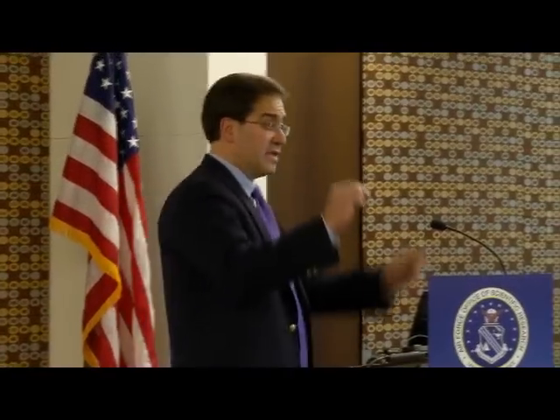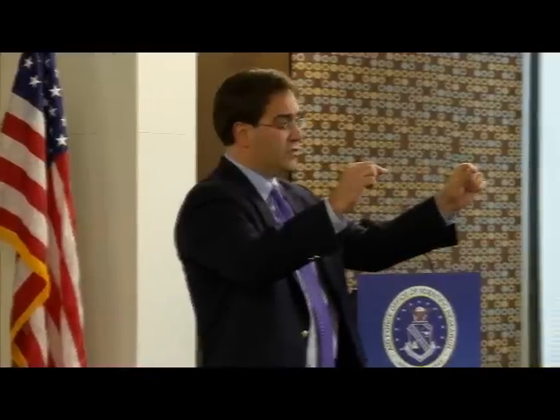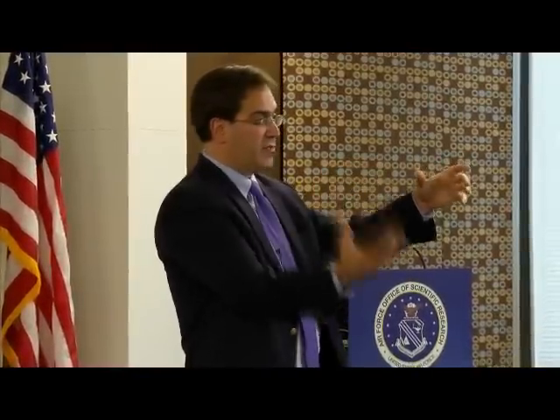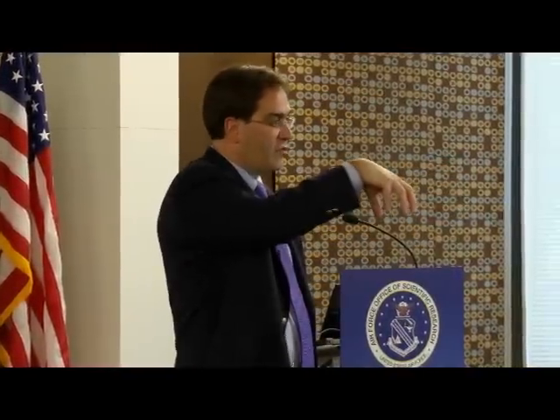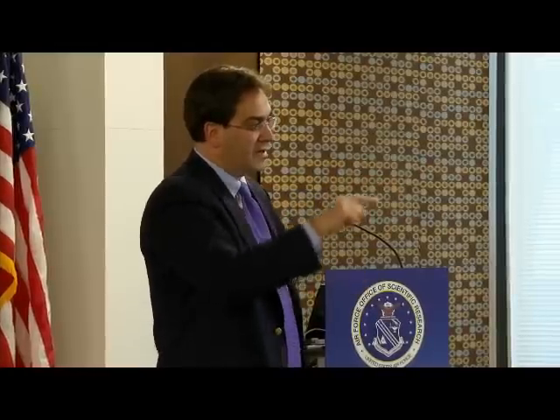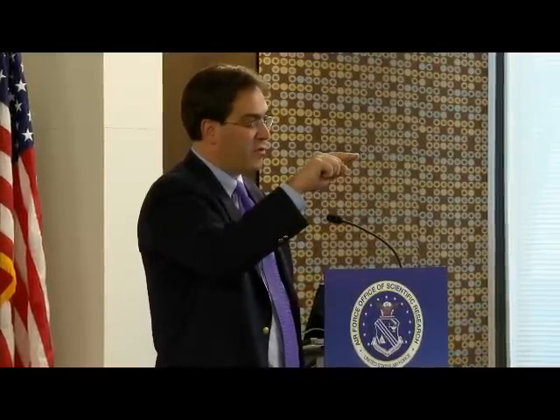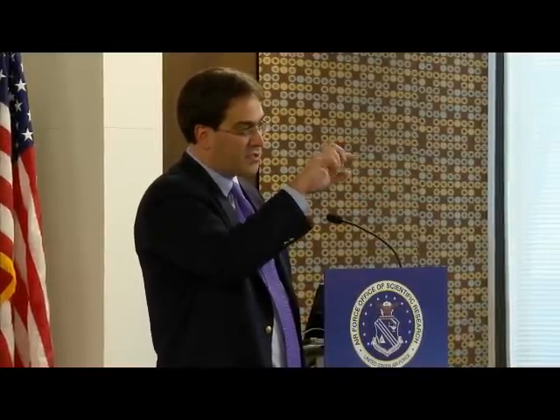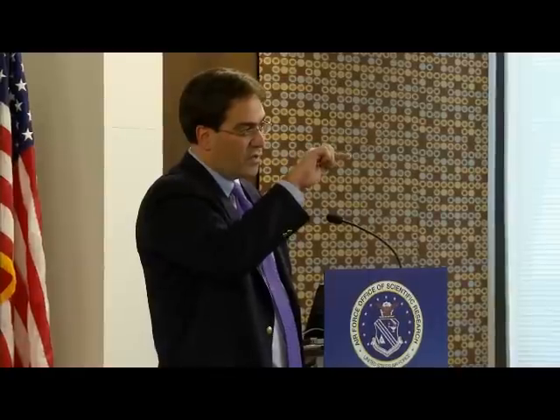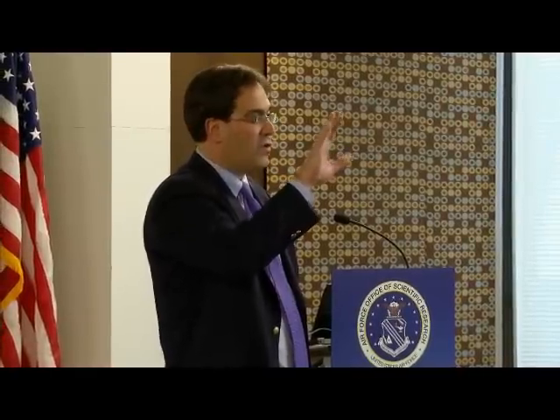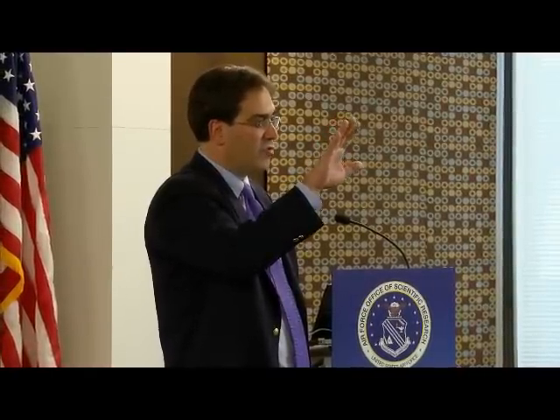And did you find that peak simply by running a lot of experiments and saying? Well, that's what I'm saying. Yeah. So we have tilt screws. And so you set this up with a scale, exactly, and you bring it down, you make a measurement. Now you adjust. And you say, are we flat? Or are we getting to a point where it's rising? And in the initial stages, when we're just tilting and changing one screw, we get a local kind of rise, and we say, oh, we're pretty good in that parameter.